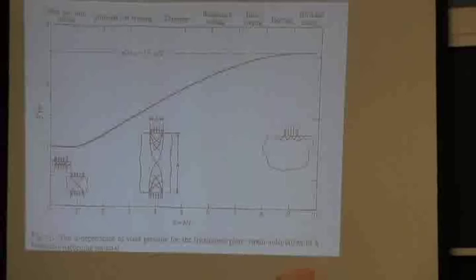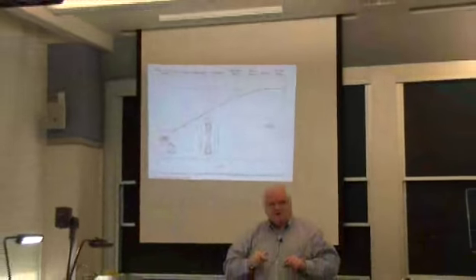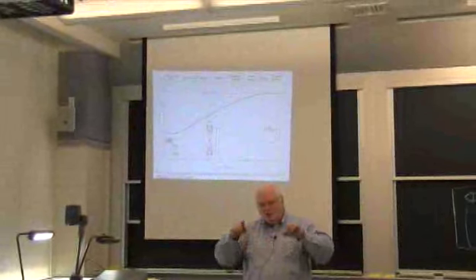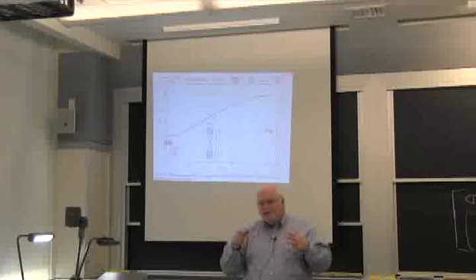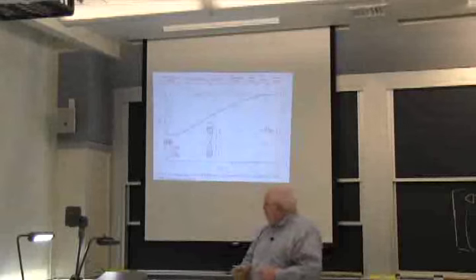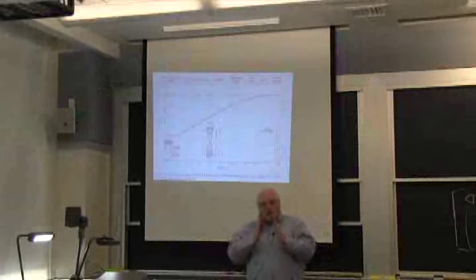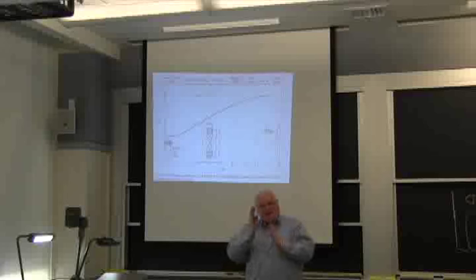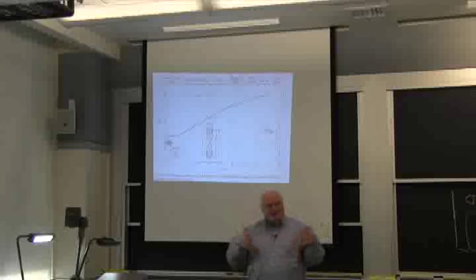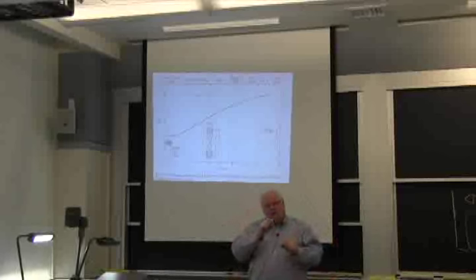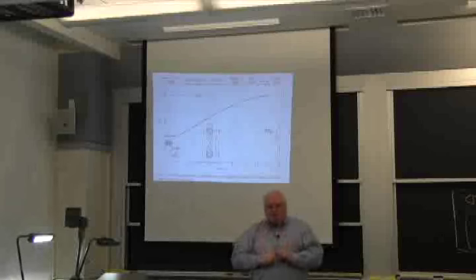Some material that starts shearing this direction later in that process has to turn and go up. I mean, the stuff at the very bottom is going down, and then it has to go to the side, and then it has to go up as I'm doing this. And as it does that, it's extruding around my fingertip, and I have what we call redundant deformation. That redundant deformation causes me to shear in one direction, shear another direction, and then shear back. To get the same initial shape change, I had to shear it 3 times to get one shape change, because the material had to flow through a complex path to get from shape A to shape B. If I took a little volume element, it had to shear in several different directions to get there.